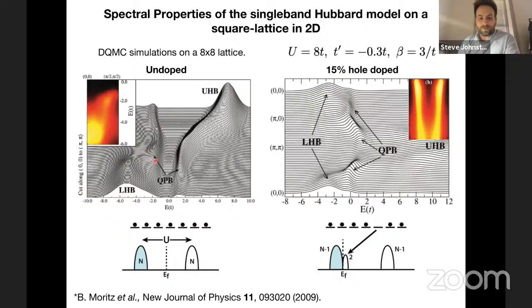And you can see here, we've got a lower Hubbard band that's very broad, well below the Fermi energy. I've got a gap of states, and then I've got another upper Hubbard band sitting up here, and these correspond to these n addition and n removal states that I had in this cartoony picture. When we dope the system in the calculations, what we find is that spectral weight is removed from both the lower and the upper Hubbard bands, and it gets transferred into this quasi-particle peak, which disperses through the Fermi energy like so. And that's, again, reminiscent of this cartoon picture that I drew here from the previous slide.